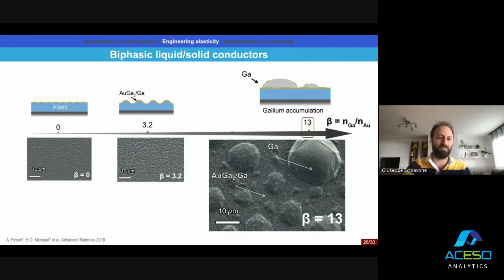We had our silicone substrate, so the elastomer that we work with is called PDMS. We applied a thin film of gold again, but the gold this time is not stretchable because we want a thicker metallization. So if you grow the gold too thick, it will not have this characteristic microcracked structure. So to improve on that, we wanted to see whether we can use the liquid metals to help us. So what we did was to deposit gallium. So gallium is a metal that is liquid at room temperature. So this is quite interesting because we can have a metal that is liquid around the temperatures that we have in the body.